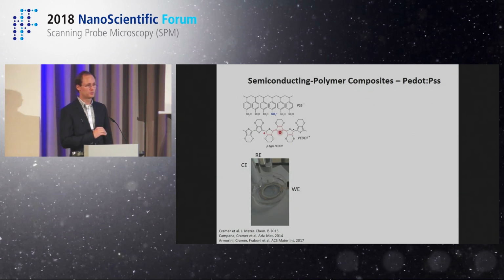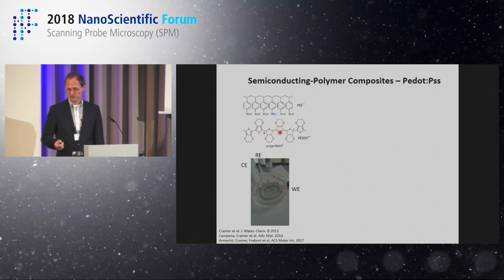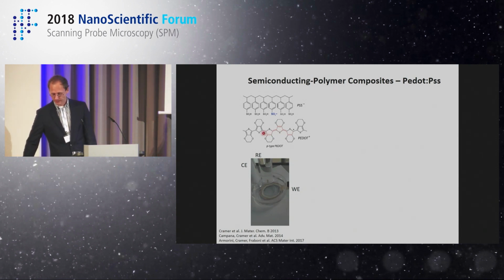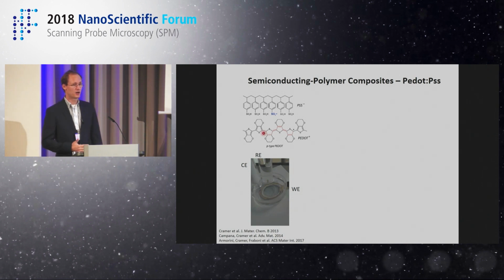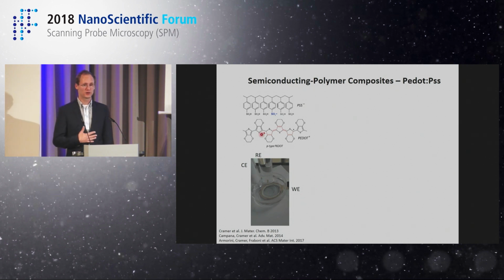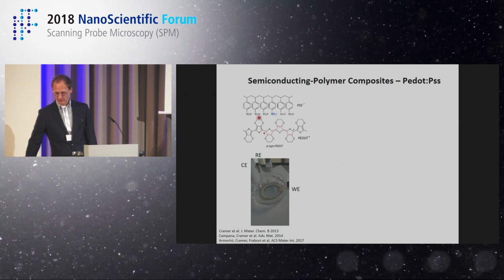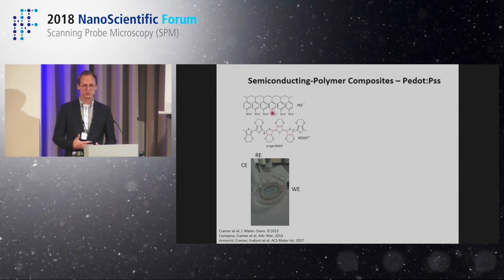So it's a polymeric material that transports hole charges, similar to something that you know just from a traditional semiconductor device. The question in these devices is, how do you introduce these positive charges? Of course, you can apply a field effect, but you can also use some kind of doping technique. And the doping comes here in the form of a polyanion. You see here that this is also a polymer which from time to time has these negative charges. And these negative charges counterbalance the mobile positive charges in your semiconducting polymer. The whole system is a kind of composite in the sense that you do not get a homogeneous mixture, but it's a material that has its own nanostructure.